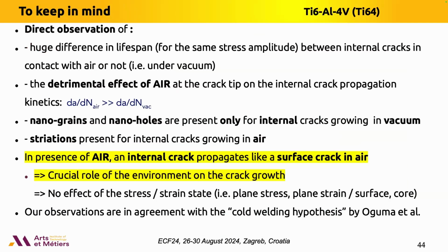So for the titanium alloy, as a conclusion, what we can say is that there is a big difference between an internal crack propagating without air or with the presence of air. The fatigue life is very, very different. So there is a detrimental effect of air on the crack propagation. As soon as there are air molecules, the speed is very high compared to vacuum. And when we are in vacuum, we can observe nanograins and nanoholes, but not when there is air. When there is air, we observe only striations.